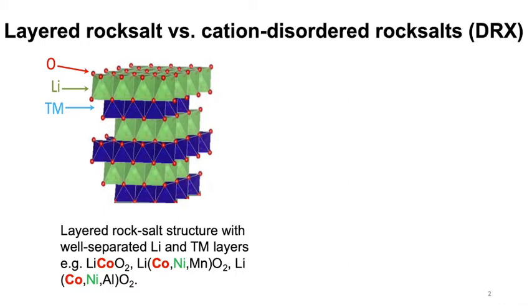Within this layered rocksalt structure, there are several types of popular chemistries, including lithium cobalt oxide, the LCO type structure, lithium nickel manganese cobalt oxide, the so-called NMC structure, and lithium nickel cobalt aluminum oxide, the so-called NCA structure. Most layered rocksalt chemistries heavily rely on cobalt, nickel, or manganese because they do not tend to migrate from the transition metal layer to the lithium layers, even after lithium delithiation. That prevents the structure from irreversible structural degradation.